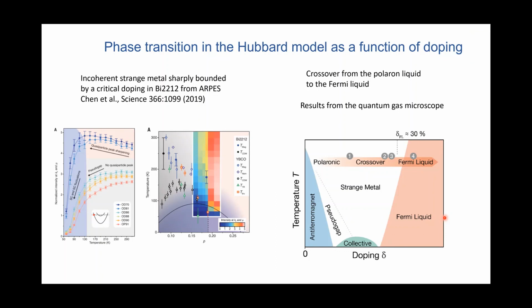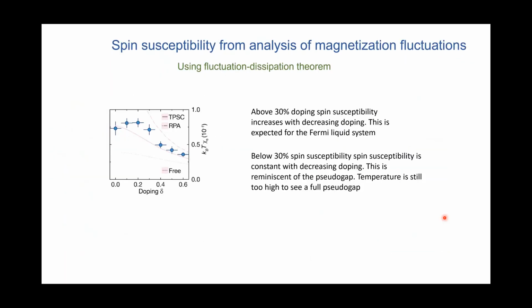What happens in this case for the transport coefficients, like the shear viscosity, susceptibility, compared to the Fermi liquid? So susceptibility is this, right? This is spin susceptibility. If you compare it to Fermi liquid, this dashed line is bare RPA, and the solid line is an improved RPA. You see that at large doping, spin susceptibility agrees with what you get from a Fermi liquid, RPA type expression, but it clearly breaks down close enough to half filling.